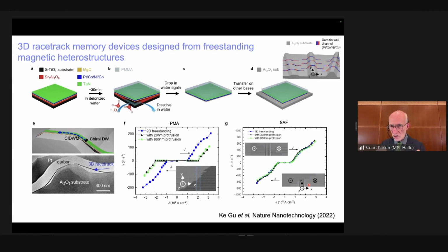This is 1 centimeter by 1 centimeter, and the membrane of the racetrack is floated off, and we float it off onto a substrate in which we pre-patterned to have a hillock, you can see in the top right, up to 800 nm tall. And in the bottom left, you can see the black line in this cross-sectional transmission electron micrograph is our racetrack. It's just a few nanometers thick. And you can see that it follows this hillock we've built into the substrate. And we've demonstrated that the domain walls move essentially with the same performance, the same velocity for the same current density as in the film before we floated it off on water. I think this is a very elegant technique.